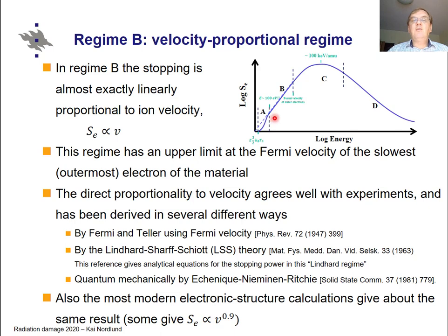Jumping down, we go to regime B, which by definition is the regime below the Fermi velocity of the outer electrons. The lower energy limit of this regime B is not easy to specify — it is roughly on the order of a hundred to a few hundred eV, but this is not really well known for reasons which I will come to when we discuss regime A.